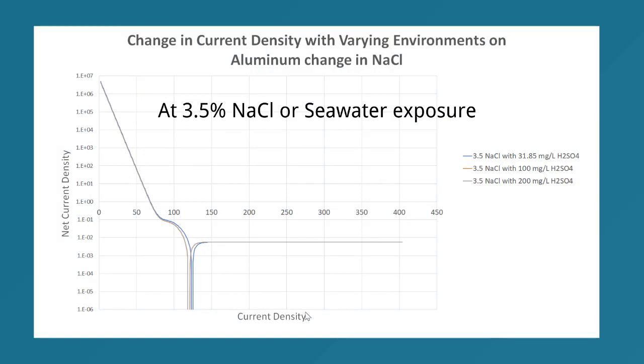Only the simulation with seawater at 3.5% NaCl, with an addition of a change of pH using different in-stream amounts of sulfuric acid at 31.85, 100, and 200 milligrams per liter, showed a plot change. However, at the other percentages of NaCl, a change of pH kept the current density at a constant rate. I would be most interested in seeing if there's an effect on the corrosion rate once zinc is brought into the picture. I will have to leave that for further future studies.